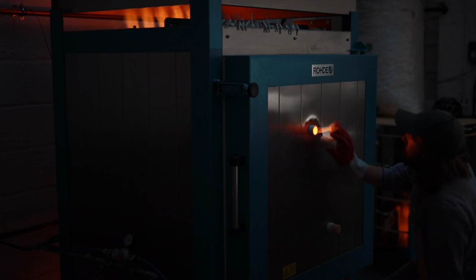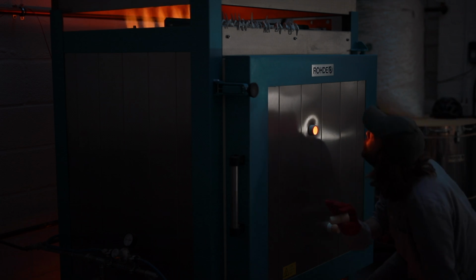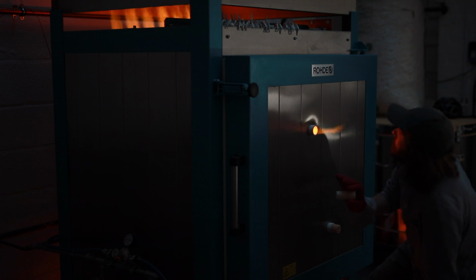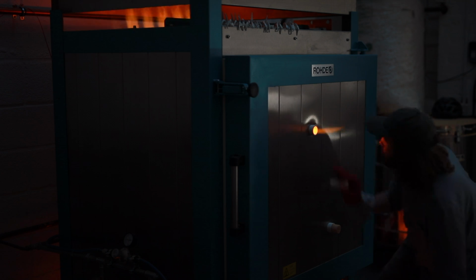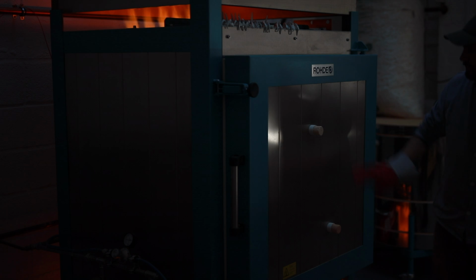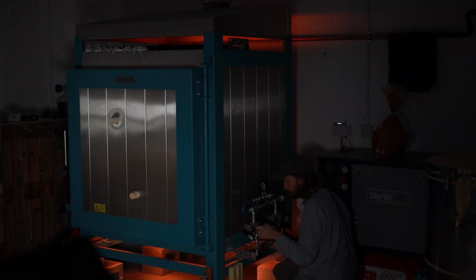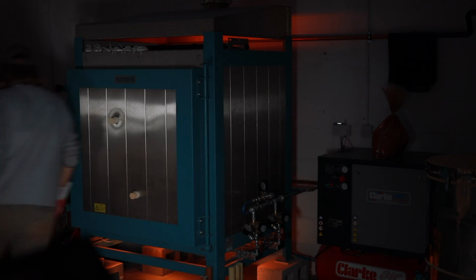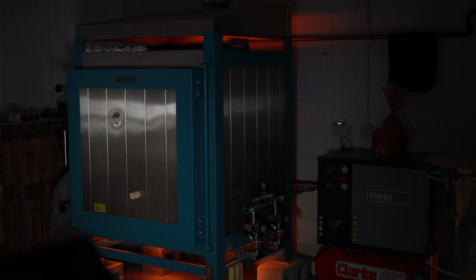Doing this reveals the area where there are small little measuring devices inside called cones, which bend over at certain temperatures. What I never noticed until filming this actually was how blowing in affects the flames that are coming out of the back. And finally, after 9.5 hours, once my cones have all bent over to the right position, it's time to close off the kiln, which is always a very satisfying moment as the noise quietens.